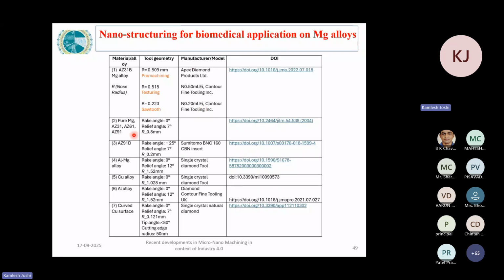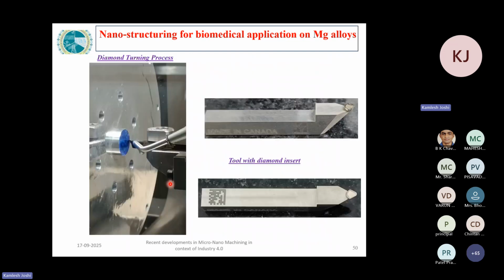Here in another paper, people have used machining of magnesium AZ31, AZ61 and AZ91. They used a radius of 0.8 mm and a rake angle of 0 degrees. In another one, Sumitomo cubic boron nitride inserts were used, and these are some of the angles. You can refer to the slide to find the range of tools which can be used for machining of magnesium alloys.